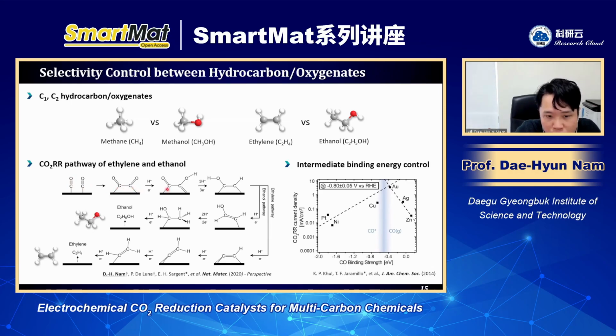And after they share the same reaction pathway, there can be the ethanol pathway and the ethylene pathway. In general, it is very difficult to control the selectivity between ethanol and ethylene, because we need to develop a catalyst which can promote C-C coupling. Also, it should be selective to ethanol, or it should be selective to ethylene.